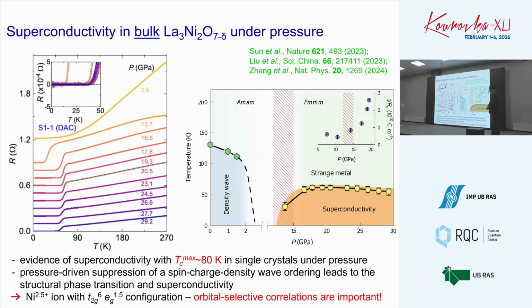Immediately, there were consistent results that upon external pressure, this material undergoes a structural transition associated with suppression of some kind of ordered phase, possibly a charge density wave or spin density wave phase. There are still debates about the origin of this phase. You end up in superconducting domes and strange metal behavior, and all these results were immediately reproduced in single crystals, in polycrystals, by many different groups. It is somewhat surprising because people now start to pay attention to the delta, the oxygen deficiency in this material, which is sometimes as high as 10%, but still these materials exhibit superconductivity, although there are some issues about the parent phases.